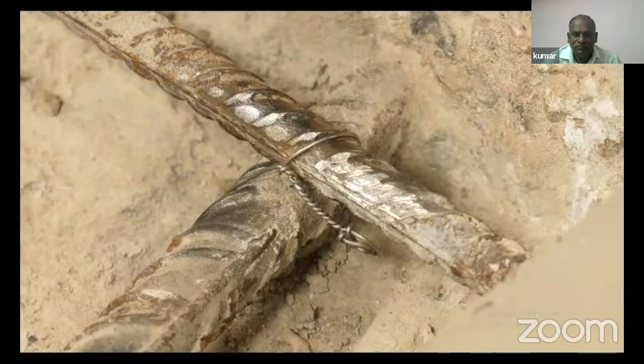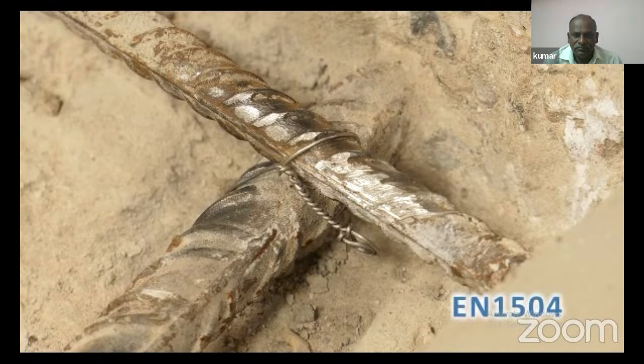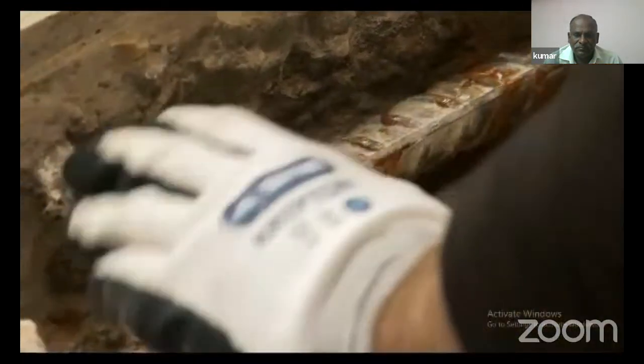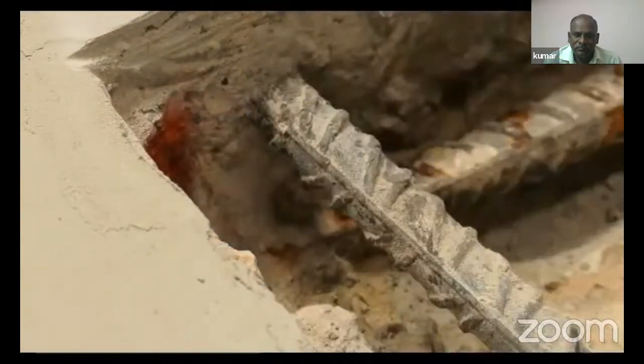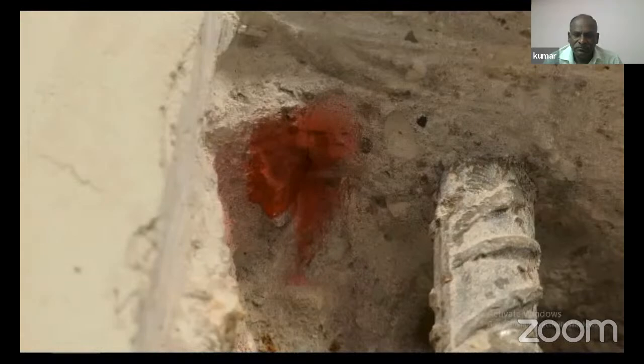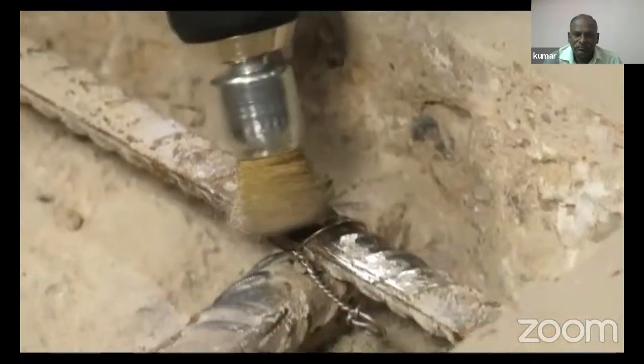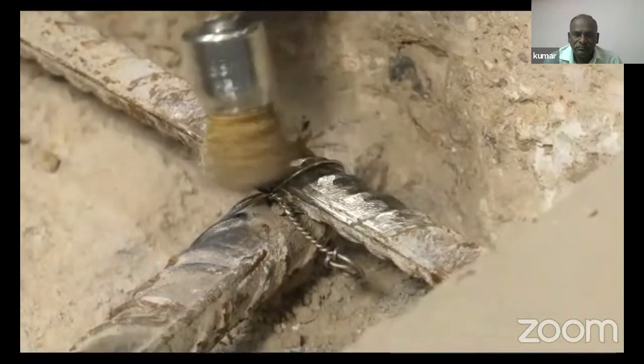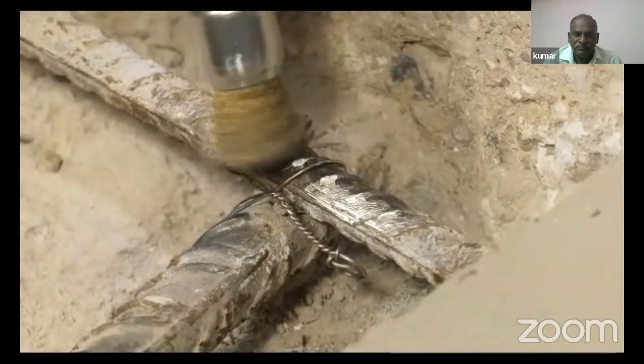Areas of concrete to be repaired should be broken out to the guidelines outlined in EN 1504. Having exposed the steel reinforcement within the patch repair area, a location for the patch guard anodes should be identified at the edge of the patch. Clean the steel in the vicinity of the proposed patch guard unit location to allow electrical connection of the anode.